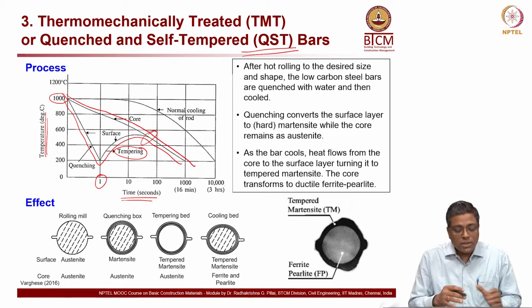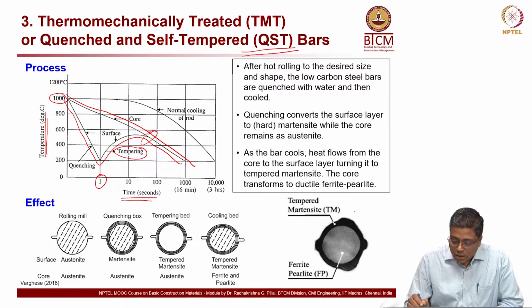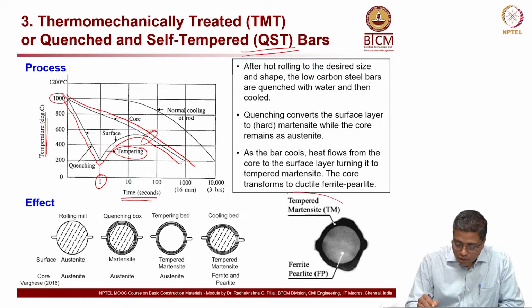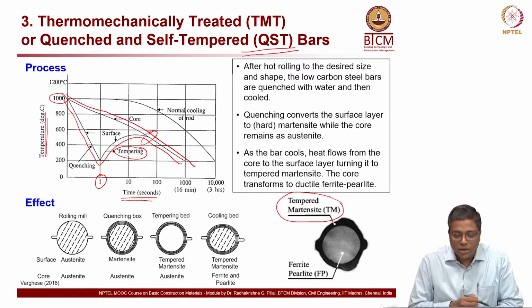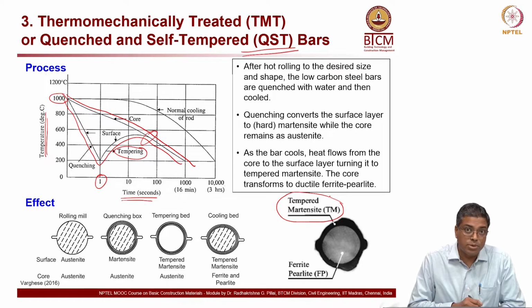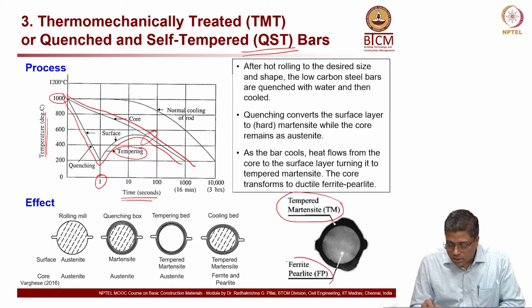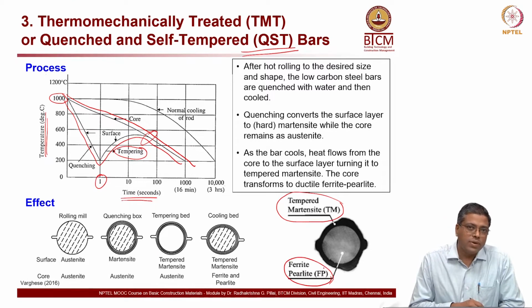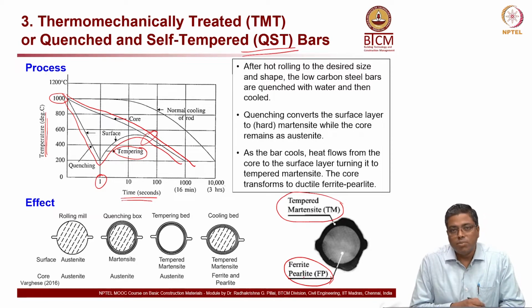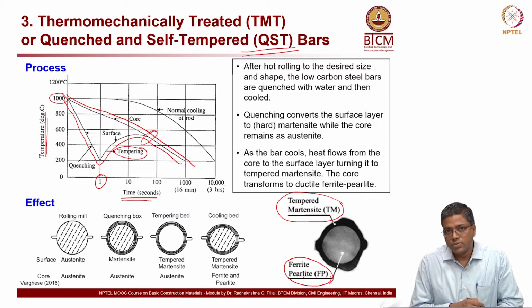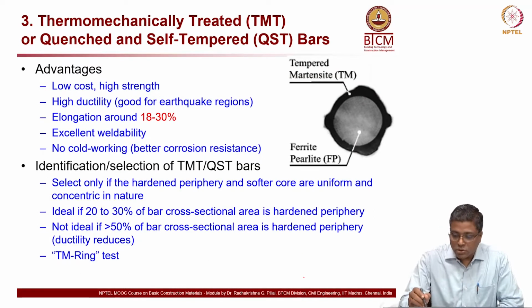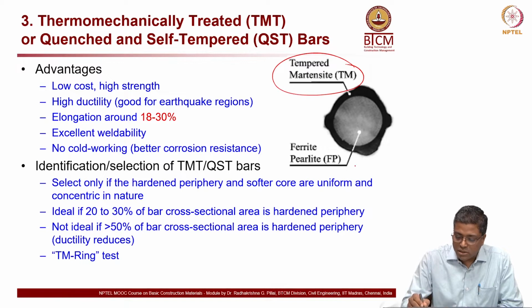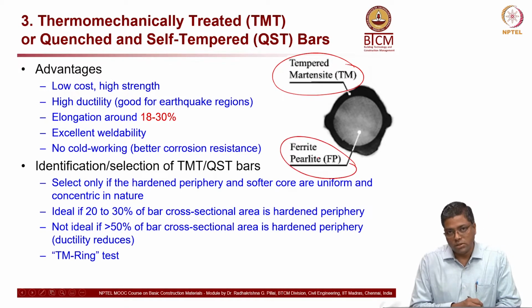Now, during this process, when we quench, the quenching and self-tempering lead to a microstructure called tempered martensite in the peripheral region, because that surface is the one which gets water, right? Now the core region is cooled in a very slow manner. That forms a microstructure called ferrite pearlite, FP. So tempered martensite on the peripheral region and ferrite pearlite on the core region.